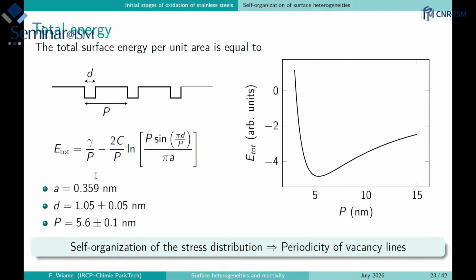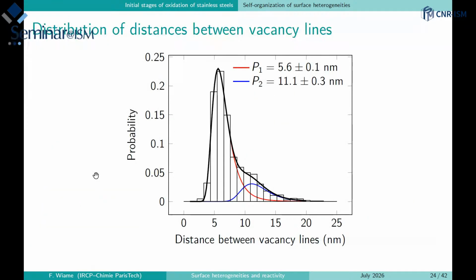In fact, if we are looking at the experimental data, and if we are drawing the theoretical shape of the distribution centered at 5.6 nanometer, it is the red one. And you have here the histogram of the measured distance, so measured over several hundreds of periods on the surface. And you can see that we have, in fact, a two-mode system, where we have a second mode which is at about double the distance of the first one.